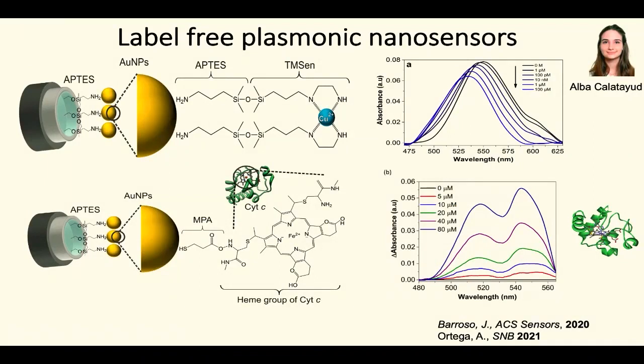So we functionalized gold nanoparticles with a kind of butylamine to complex copper. And you may know that the copper complexes have a UV-Vis absorption spectrum around 550. So what we saw in the presence of copper is that the typical plasmonic peak of the gold nanoparticles was decreasing and was shifted to the blue, indicating the presence of the copper. If we wash the fibers and remove the copper from the gold nanoparticles, we recover the spectra typical of the gold nanoparticles.